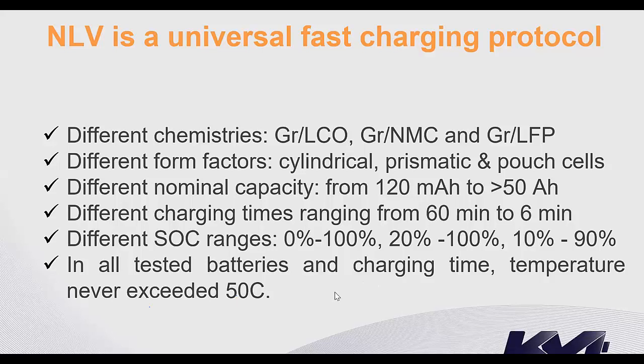The very, very important thing is that whatever the charging time, whatever the chemistry of the batteries, we never exceeded 50 degrees C when we charge them, okay? And 50 degrees C is considered for us as the safety limit. We don't want the battery to heat up more than 50 degrees. Although some manufacturers like Samsung told us that we can go to 60 degrees without any problem, we decided never to go higher than 50 degrees.